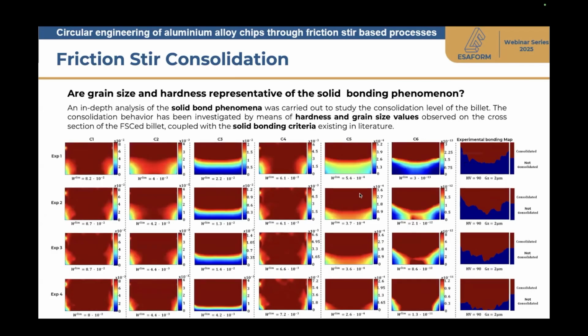Namely, the last column shows the experimental results in terms of consolidation or not consolidation, giving or introducing a threshold in the local value of the hardness of the consolidated material. And in turn, the first 6 columns give us the results in terms of the value of the criterion, the threshold of the criterion reached during the process. It should be observed, at different stages of the processing times.